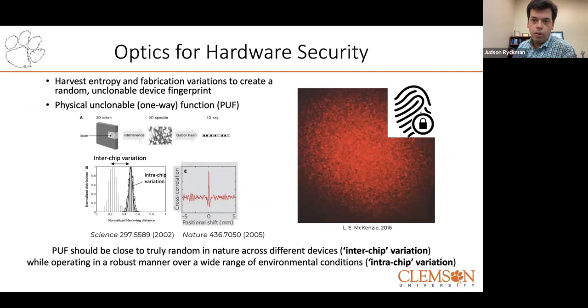So optics has begun to play a role in this field, and this actually started in the early 2000s with the idea of a physical unclonable function. And so this can be as simple as taking a rough optical surface and shining a laser beam off of that surface and looking at, say, the speckle pattern. So you'll get this very information dense, information rich pattern that should be unique to that particular rough surface. And you can extract information from it.